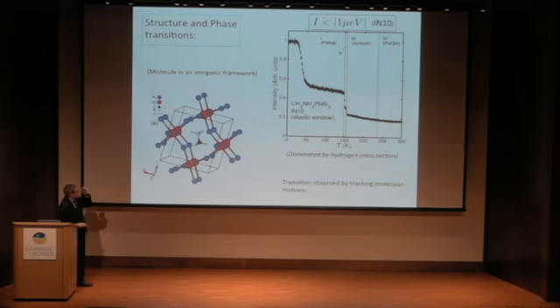Okay, so this is some data that I want to start off with showing. This is a powder of methyl ammonium lead bromide. This, again, is the basic crystal structure of the unit cell. You have your bromide framework, and you have your lead, which is these big red ions. And inside this framework, you have this methyl ammonium molecule. What I plot over here is intensity as a function of temperature, taken on the IN10 spectrometer. It's kind of a strange scan because it's called an elastic window scan.